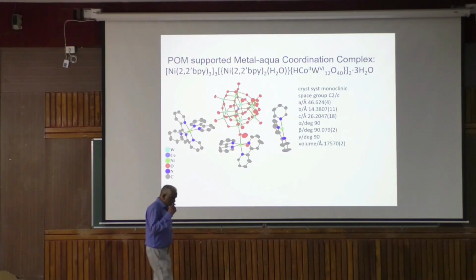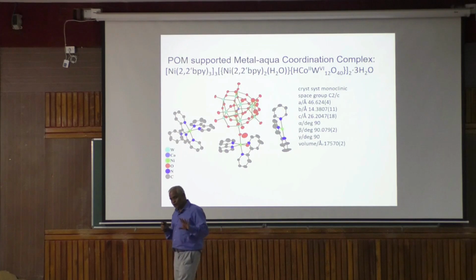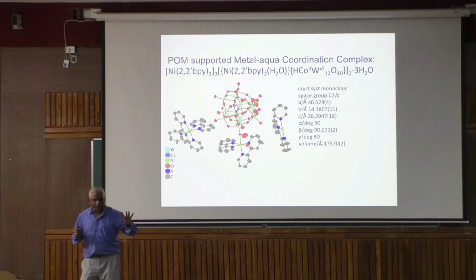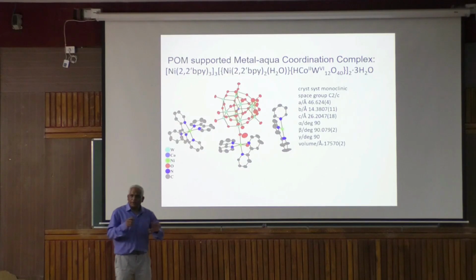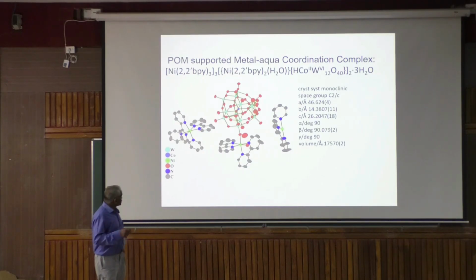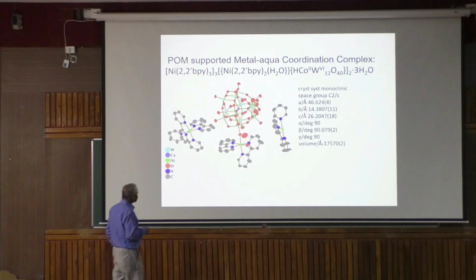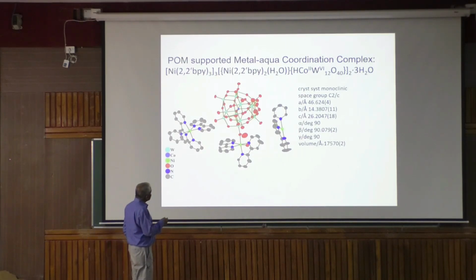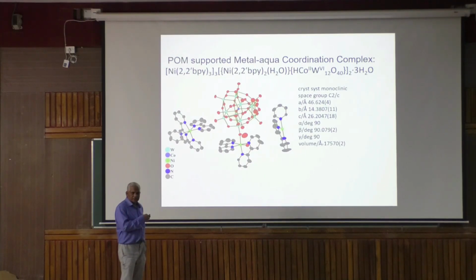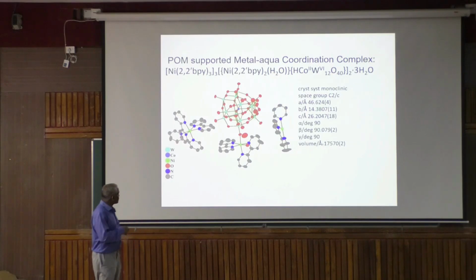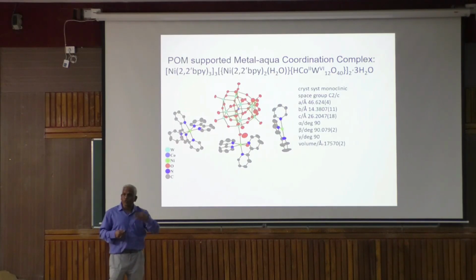So what we did, for many years since I joined University of Hyderabad, we have been doing a lot of polyoxometalate clusters, crystallography, supramolecular chemistry. But we never checked water oxidation because we did not know that. So recently we were trying to check, and what we found is that this compound you can make as a potassium salt, water soluble. You can get the ready-made nickel bipyridyl 2 chloride salt, water soluble. To attach by coordinate covalent bond, as if the cluster is acting as the ligand, isn't it? Oxygen lone pair coordinates to the metal atom and makes a very stable heterogeneous system, water insoluble. Now if you coat this compound on the electrode surface and do water oxidation, let us see.